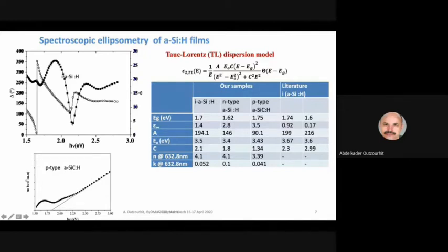The row here also gives the refractive index and the extinction coefficient at a particular wavelength. As you can see, the refractive index of the films is around 4.1 for the hydrogenated amorphous silicon films, and 3.39 for the P-type hydrogenated amorphous silicon carbide film.